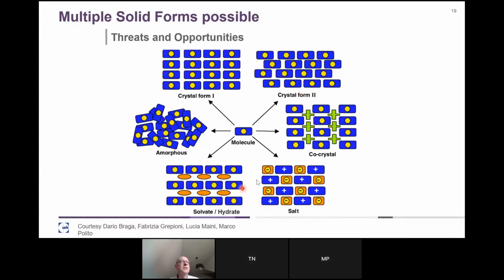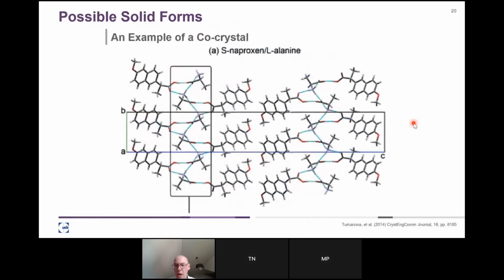So all these forms that might arise give you, of course, the possibility to tune the properties of the crystals. So you could go deliberately to one of these to get the solubility that you want, to expose the patient in the right way. You can even keep it amorphous, which per se is not stable, but that way you could expose more. But it's also a threat, because you might suddenly, without wanting it, have these crystals appearing, for instance when it happens with an excipient that is in your tablet. So we need to watch out for this. This is just to show you that the other molecule is really incorporated in the crystal. So it's really taking its place in the 3D structure.